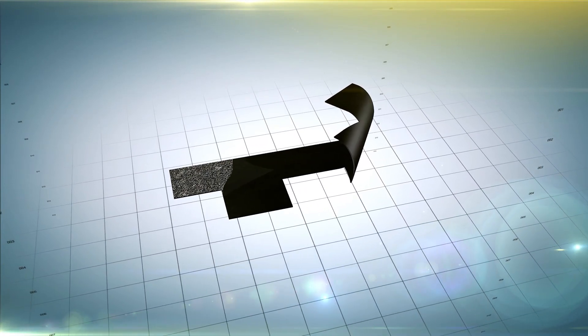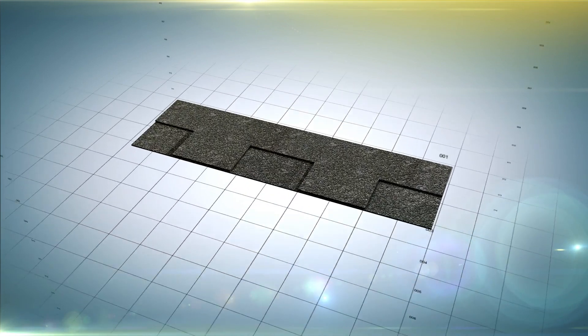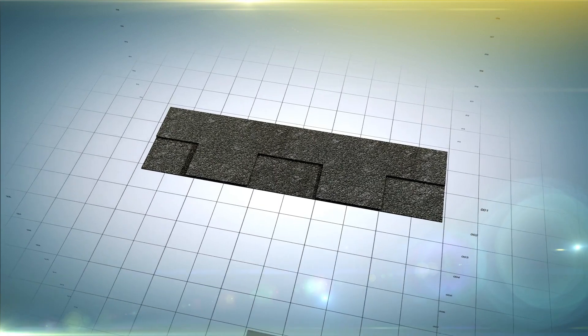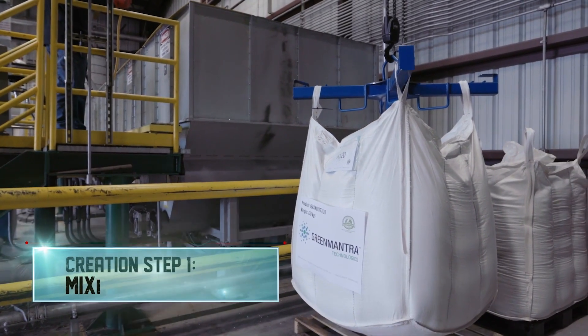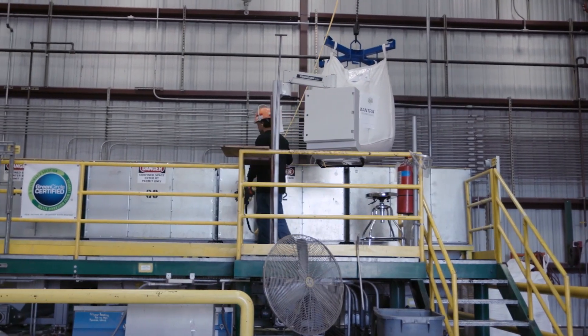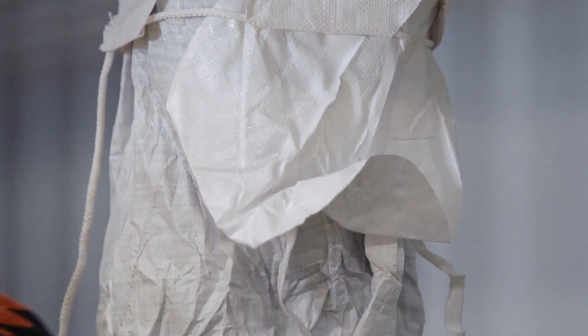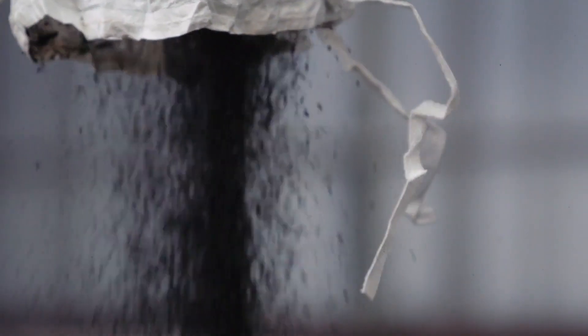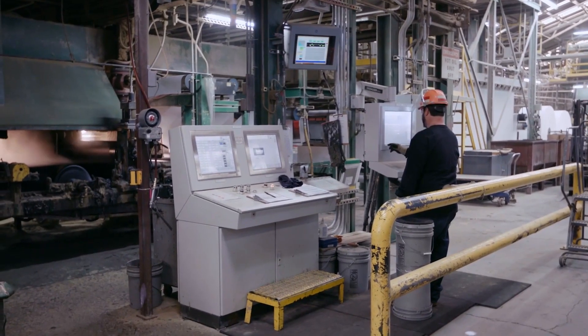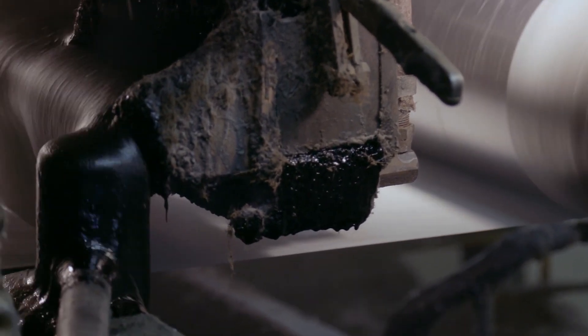The shingles are manufactured with a fiberglass mat that's coated with a liquid wax and asphalt blend, a layer of ceramic-coated granules, and finally a sawtooth top layer laminated to a solid bottom layer. The first step in making a shingle is to melt the polymer pellets — a worker opens the bag and releases the polymer beads into the mixer, which is heated to 93 degrees Celsius and blends the polymer pellets with asphalt.